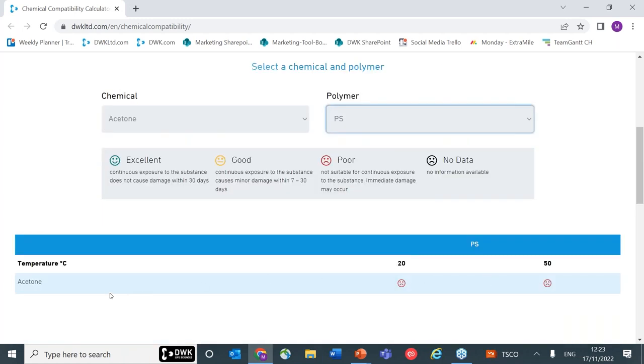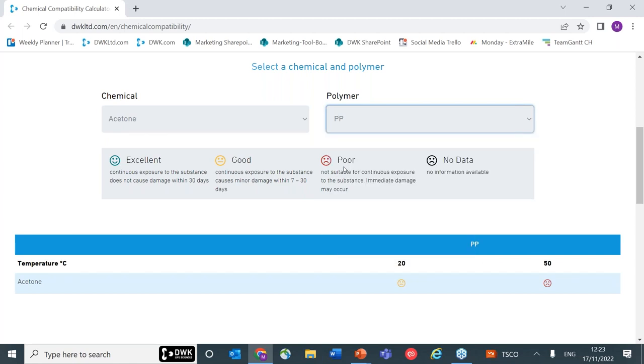So it shows that the polystyrene vessel or container isn't suitable for use with acetone, either at room temperature or at elevated temperatures. Maybe if we have a look at polypropylene, for example, polypropylene has good chemical resistance at room temperature.